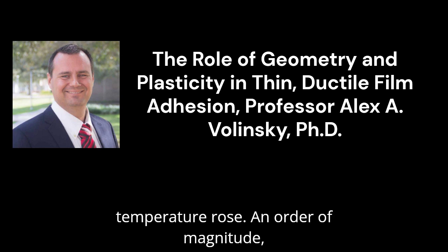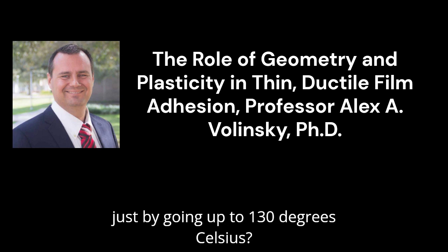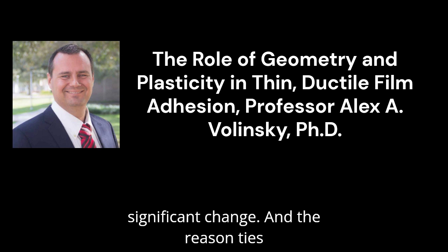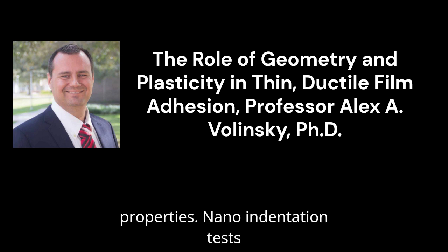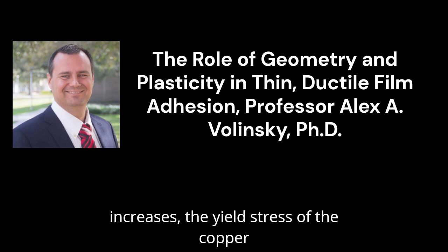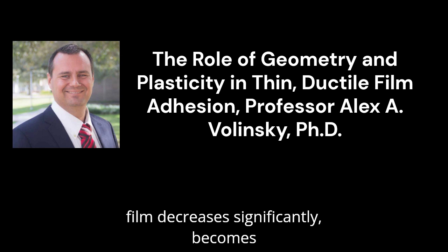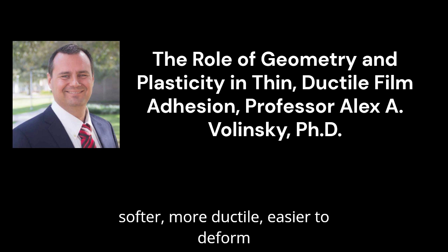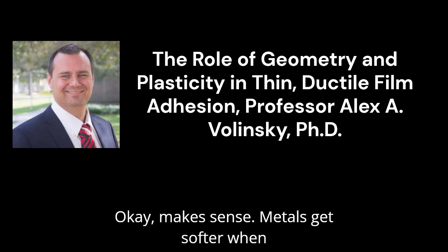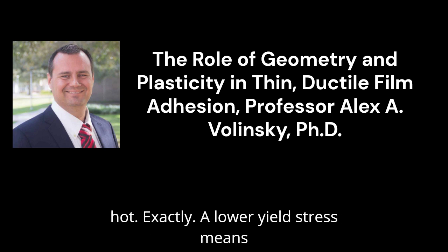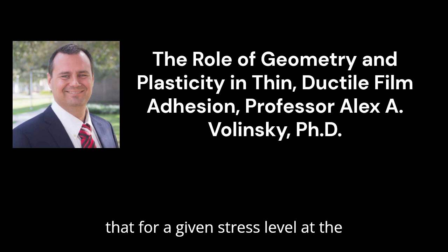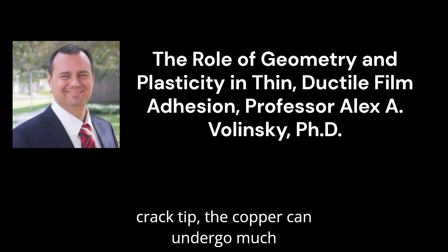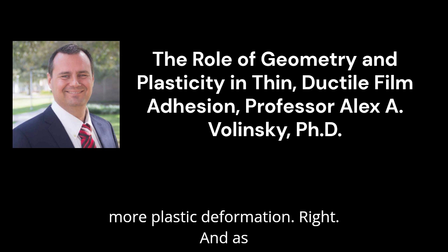An order of magnitude? Yeah. Just by going up to 130 degrees Celsius? That's a huge effect. It is a really significant change, and the reason ties directly back to the material's properties. Nano-indentation tests confirm that as the temperature increases, the yield stress of the copper film decreases significantly. It becomes softer, more ductile, easier to deform plastically. Okay, makes sense. Metals get softer when hot. Exactly. A lower yield stress means that for a given stress level at the crack tip, the copper can undergo much more plastic deformation. Right.